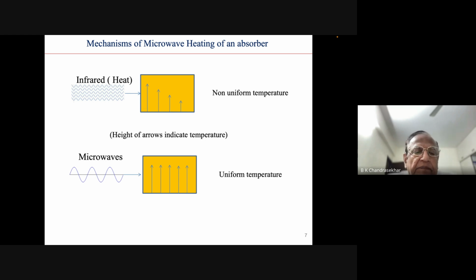Whereas in the case of microwave, it penetrates the sample inside. Therefore, the difference in temperature from the surface to the interior is very much reduced or almost non-existent. In fact, in microwave heating, the surface is slightly cooler than the interior of the sample. This lower temperature at the surface happens mostly because the surrounding atmosphere is cooler, whereas the inside is thermally insulated, therefore it becomes very hot. So this gives you an idea about why microwaves provide uniform heating and uniform temperature in the samples. This is extremely important as the sample size becomes bigger and bigger.